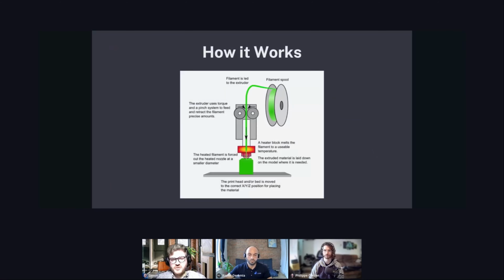So what's material extrusion? In short, it's a process where a raw material is taken, here on the slide, in the form of a plastic filament, but sometimes it could be powder, pellets, or even paste. And that material is fed through an extruder, a mechanism that is moving the material to a melting zone. In this example, the extruder is a pinch system grabbing the filament and then bringing the material in the melt zone, sometimes called a hot end, and deposited through a nozzle on a surface to create a shape layer by layer.